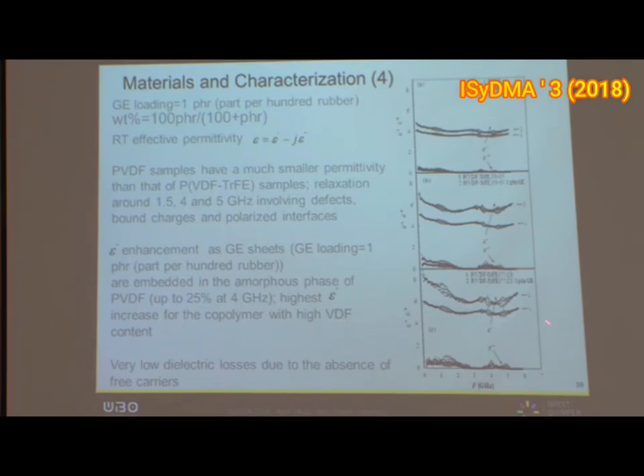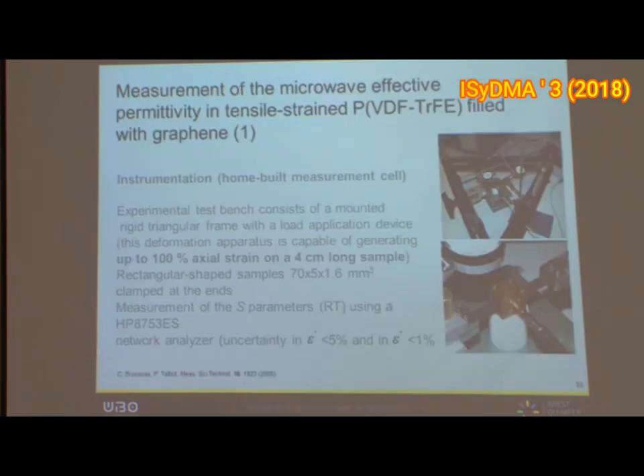Another remark, which is also important, is when you change the VDF ratio - I mean the copolymer ratio in your system - you can have different behavior because this ratio directly impacts the crystallinity of the system. And remember that the graphene particles are embedded only in the amorphous phase of the system.